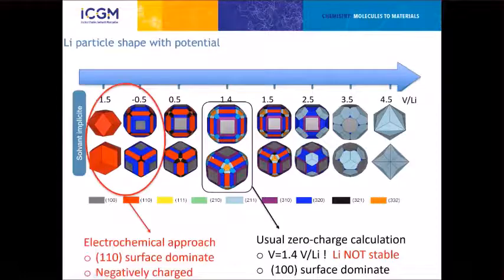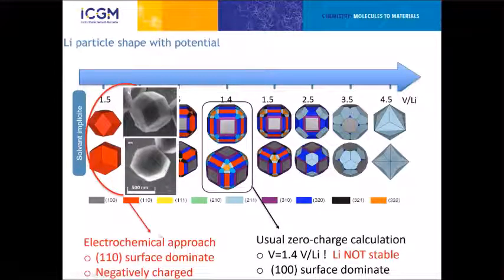So to get to a really negatively charged system, going to zero relative to lithium, we can get a charged system, and we find that we get a completely different surface. When it's uncharged, it's a 1-0-0 surface that dominates the energetics, and when it's under reduction, under negative potential, it's a 1-1-0 surface. And in this case, you see that we are able to reproduce the shape of the lithium particle. So it's one thing to say that charged surfaces are really important to get proper surface and interface energetics.